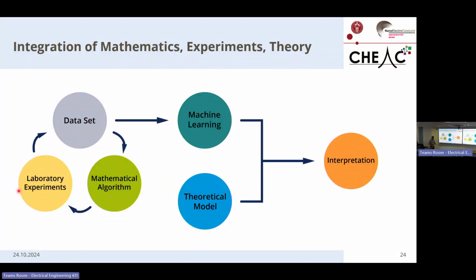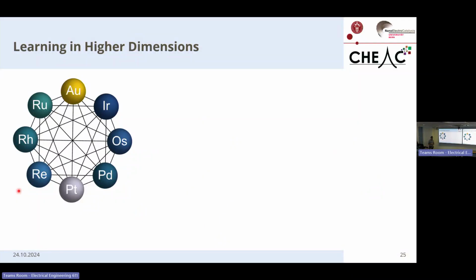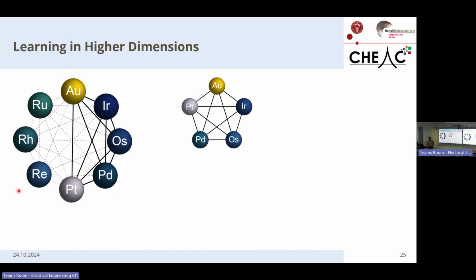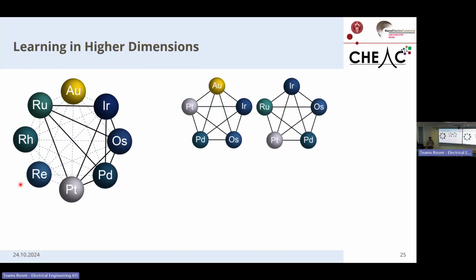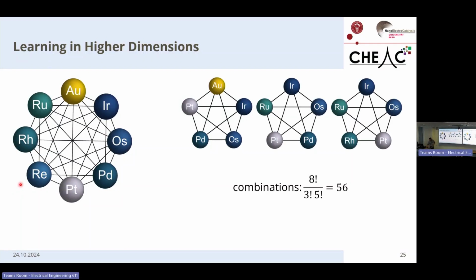So myself, I am an experimentalist, and my biggest interest is in looking at how we can optimize the generation of new data. And the question that automatically pops up is that once we have found a way to construct models for five-element systems, why should we limit our studies to 5-element systems and not go up? For this, I would like to discuss this question using this example. So let's say we have a model for this gold, iridium, osmium, palladium, platinum, rhenium, rhodium, ruthenium space. If we know the model for this space, we should inherit the model for the gold, iridium, osmium, palladium, platinum space. Likewise, for this space, that space, and in total there are 56 5-element spaces trapped in this 8-element space.